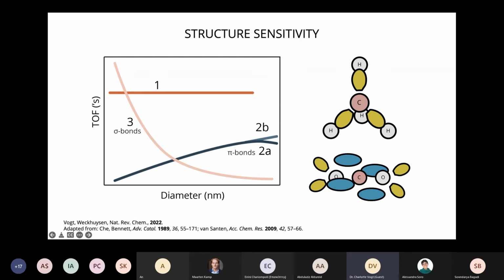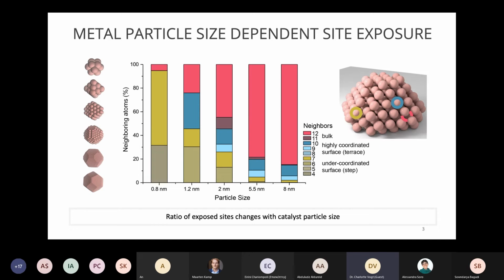And then we have this other class of structure sensitivity, structure insensitivity, where basically the activity of a catalyst does not change with catalyst particle size, which is an interesting phenomenon. Examples of that type of structure insensitivity are, for example, the recombination of an adsorbed alkyl on the surface of a metal, which is an important step in ethene hydrogenation. So a little bit about why that exists. Why do we see that phenomenon?